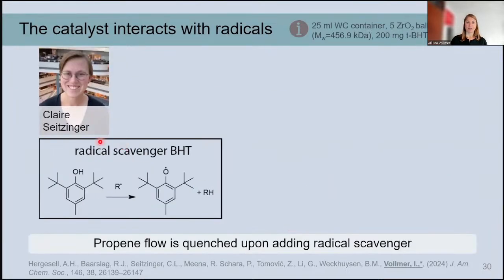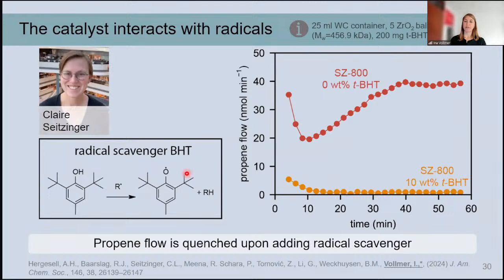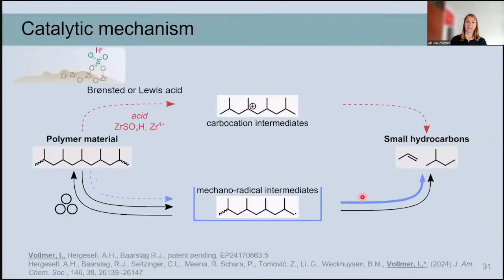And this was work that a postdoc in our group did, and she used BHT, which has this OH group here, which easily gives off this hydrogen to the radical, and thereby the radical is actually terminated, and we create this very stable radical. And so when she added this BHT to the milling, we could actually see that without the BHT, we see the propene, but with the BHT, we suppress the propene formation entirely. And so this indicates that indeed, at some point in the mechanism, there has to be something with radicals.